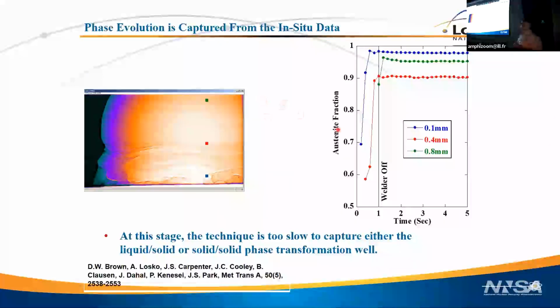So one of the first things you might want to pull out are the phase fraction. So stainless steel solidifies. If you're doing it right, it starts off in ferrite and then transforms to austenite. We get it kind of partially along the process. We never see liquid in these, by the way. We're not fast enough to see the liquid material.